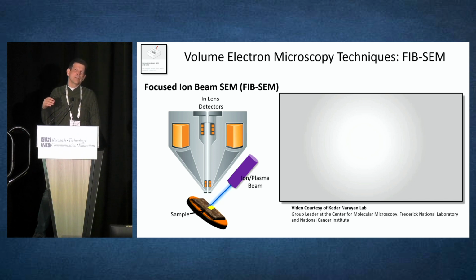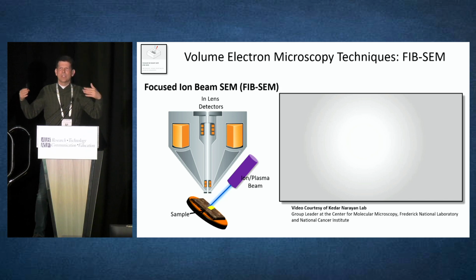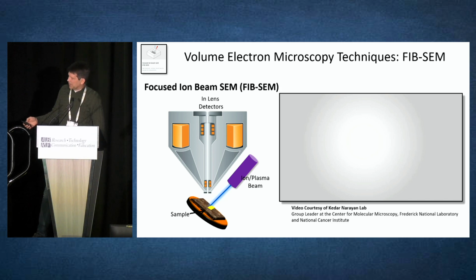The other advantage is that, of course, the resolution of a scanning electron microscope is down to about a nanometer or two, plus or minus. With an ion beam, you can now get isotropic voxels. So you can look at your structure, and they'll have the same dimension in X, Y, and Z. That's not quite possible when you're trying to do the highest resolution work with a diamond-based sectioning tool.